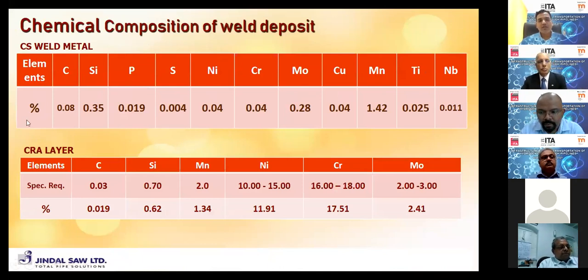So we have achieved the chemistry of the CRA layer as required per API 5LD, the specification for clad pipe manufacturing. The nickel requirement is 10 to 15, and we achieved 11. The chromium achieved is 17.51, and moly is 2.41. So that is within the standard requirement.